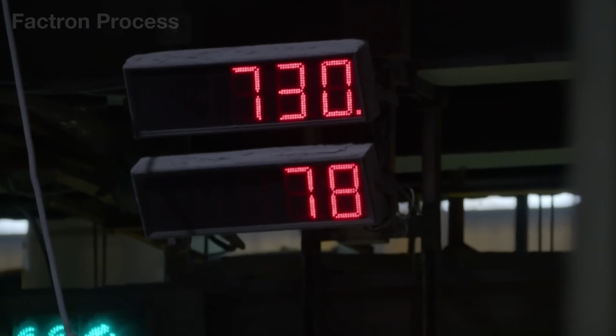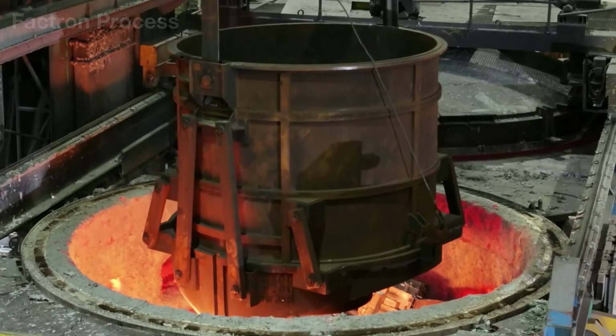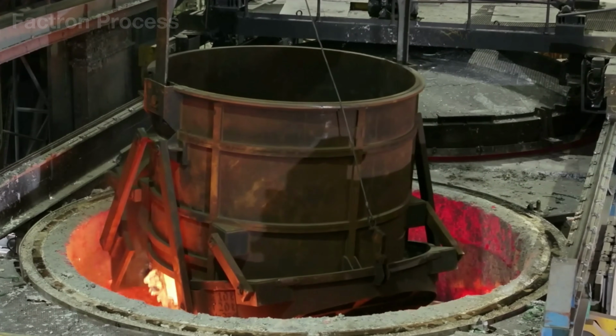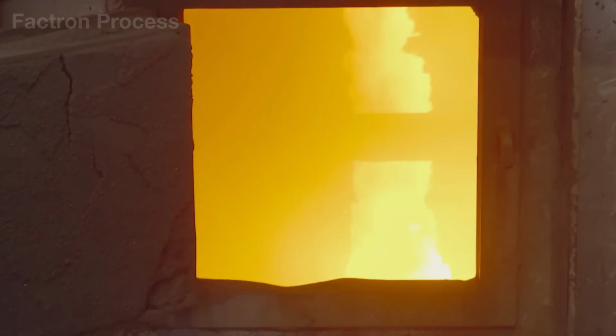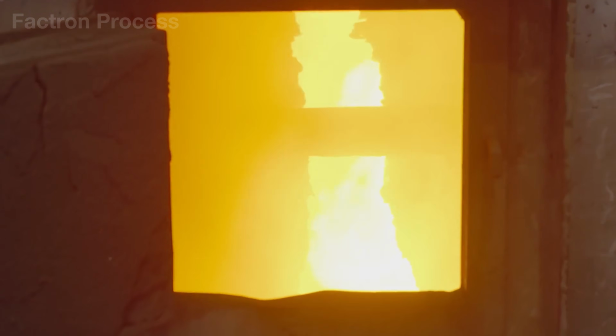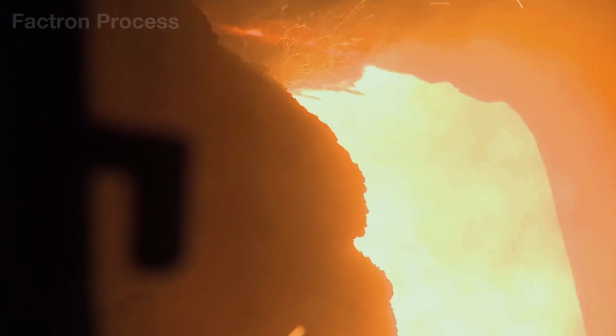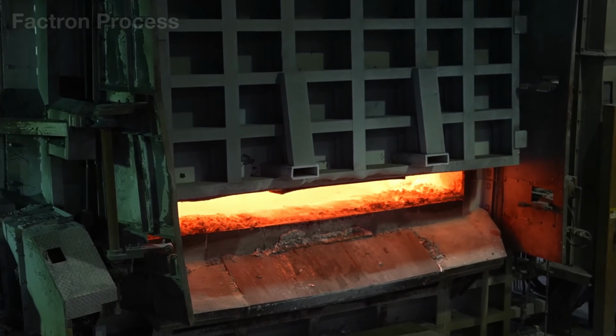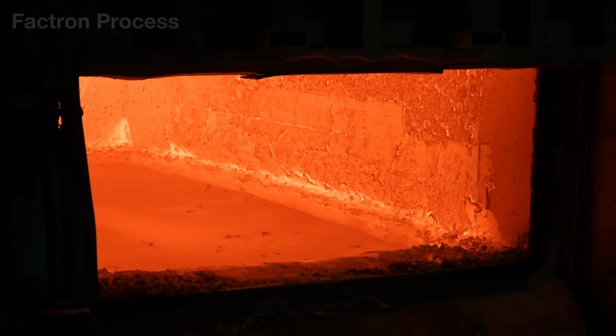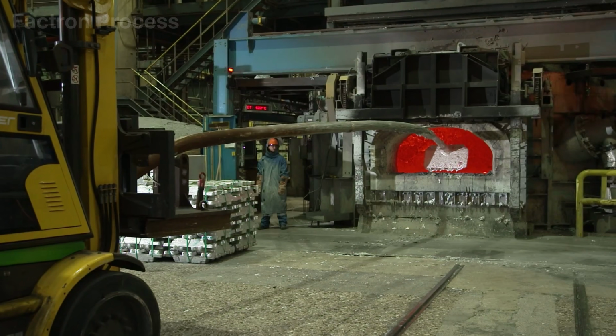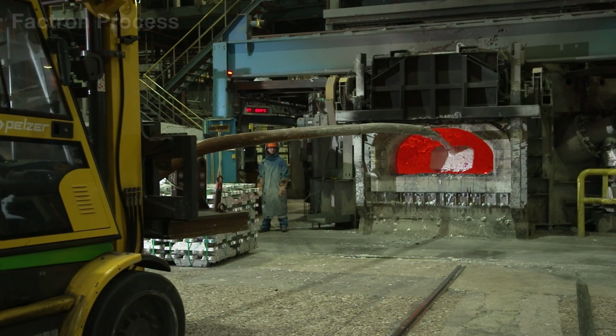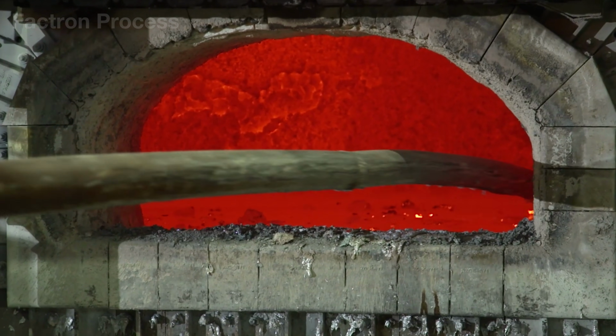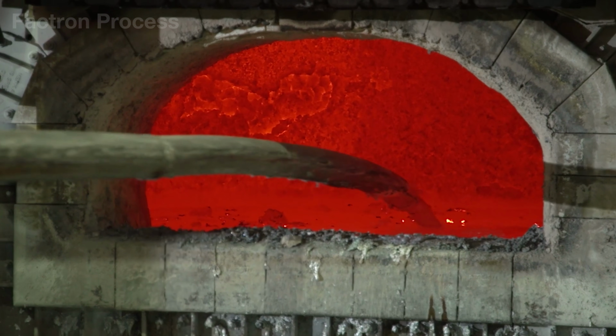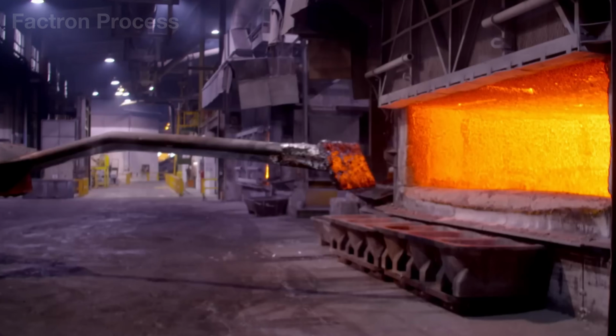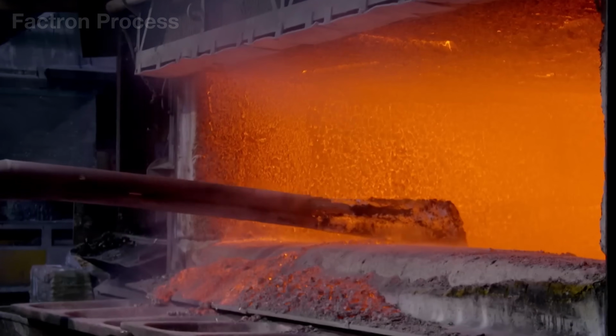The material is charged in stages to prevent the temperature of the molten bath from dropping too suddenly. Agitators and circulating currents draw the scrap beneath the surface, helping it melt faster while limiting its exposure to oxygen. Even so, some of the aluminum still oxidizes and combines with dust and other impurities, forming a layer of dross that floats on the surface. A heat-resistant steel skimming machine slowly removes this layer from the furnace. Because the hot dross still contains a significant amount of trapped aluminum, it is pressed or further processed to recover the remaining metal before it is returned to the melting bath.